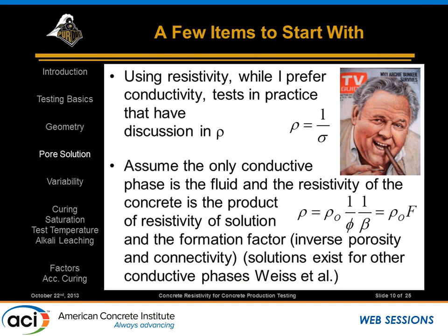Now, the other thing that I want to start off with, and I want to try to drive this home, a lot of what we're going to talk about is based on Archie's law. Not this Archie, a slightly different Archie. But the basic idea here is we're going to talk about the resistivity, and as we've heard a couple times, it's going to be related to the pores, it's going to be related to the connectedness, and it's going to be related to the pore solution property.